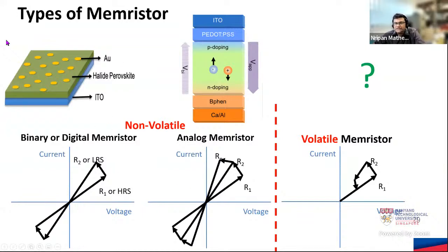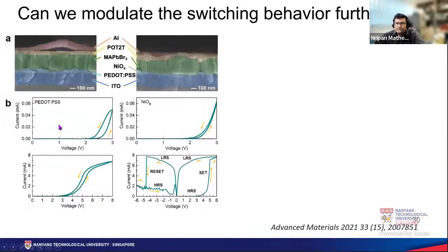So we went from a binary or digital memristor to an analog memristor. We also wanted to explore whether volatility can be controlled in our memristors. So what we did was to again work with this perovskite MAPbBr3, except we changed the interfaces. In one case, we use this PEDOT:PSS interface, and in another case, we use this nickel oxide interface. The PEDOT:PSS and the nickel oxide interfaces behave similarly at low voltages, but at high voltages, you can see that the PEDOT:PSS still remains volatile, while the nickel oxide starts to switch to